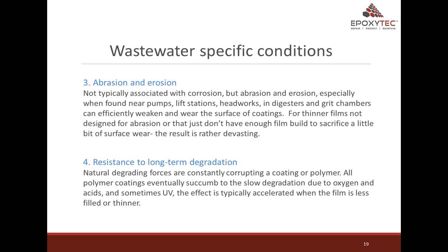Number three, abrasion and erosion. Not typically associated with corrosion, but abrasion and erosion, especially when found near pumps, lift stations, headworks, digesters and grit chambers, can effectively weaken and wear the surface of the coating. For thinner films not designed for abrasion, or that just don't have enough film build to sacrifice a little bit of surface wear, the results can be rather devastating.